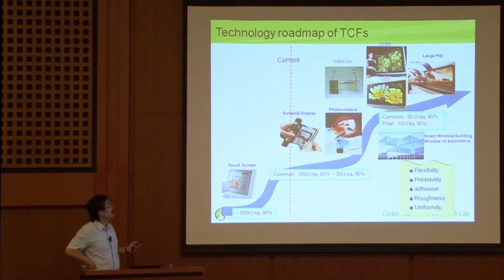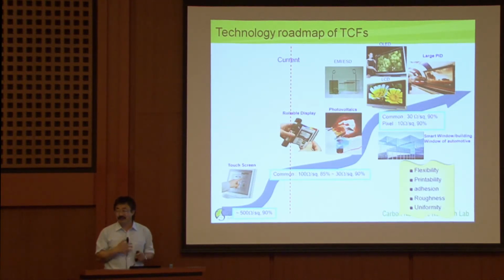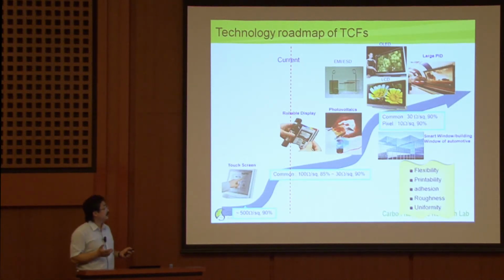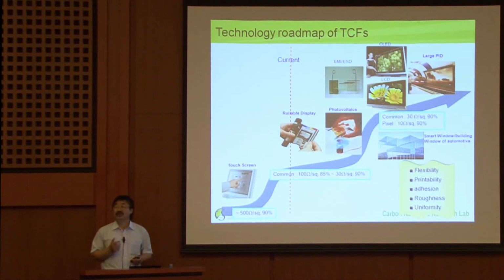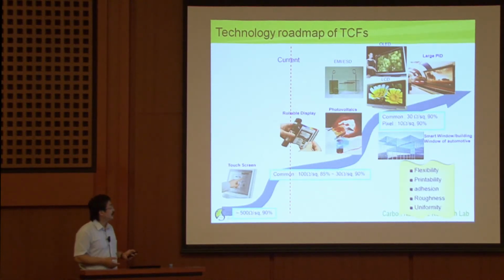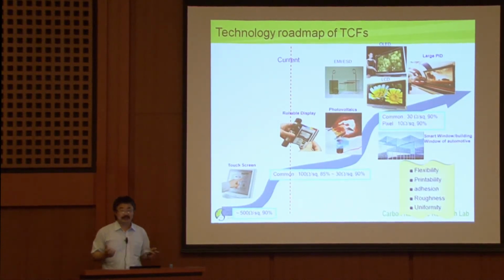So if you have that, you can have this touch screen, and in the future, of course, you can use this material for some rollable display or e-paper, whatever can be bendable. Of course, then the question is the performance of the film. For instance, if you have 500 ohm per square at 90% transmittance, you can use it for a touch panel. If you improve the characteristics of this film, then you get something like 30 ohm per square. The best quality of indium tin oxide is like 10 ohm per square. So we cannot compete at this moment with ITO. But if you go for a flexible display, then there is a different story, because ITO cannot be bendable. Anyway, if you improve the conductivity of the film, then you have many different areas for applications.